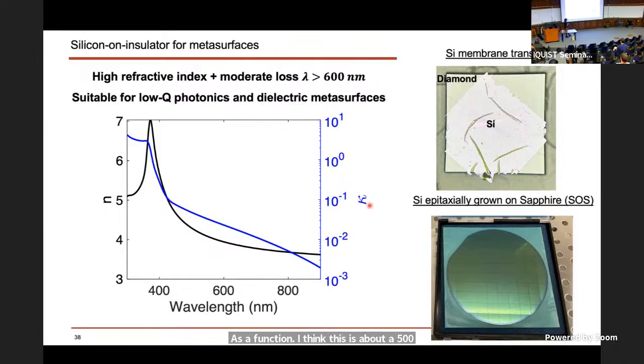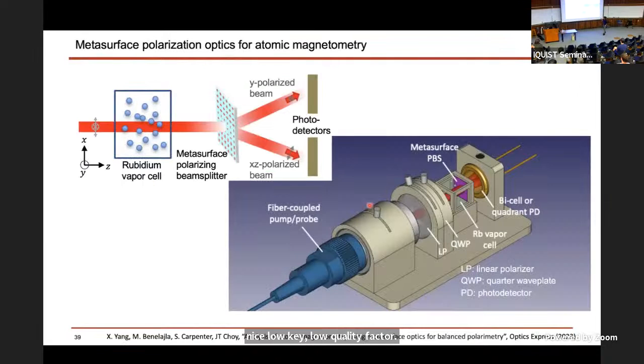As a function of wavelength, you see that you get a nice high refractive index, well over 3.5, and comparatively low loss. And so even though this will not get you the longest propagating waveguide, you actually get to make pretty nice low quality factor photonics using this platform. And one of our group's recent works is to demonstrate this by making a silicon on sapphire metasurface polarizing beam splitter that we use in combination with a vapor cell magnetometer based on rubidium.